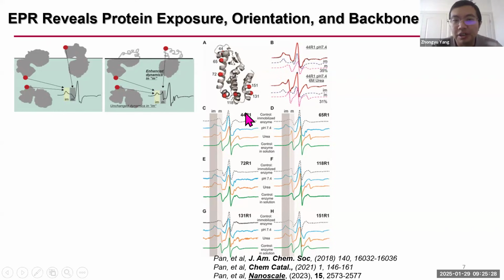But through the whole protein, multiple sites show similar percentage. There are other sites that show much less percentage of exposure. And that means orientation cannot be uniform. It's got to be random. Meaning there's no site that's completely buried, 100% buried. So the orientation is more like random.